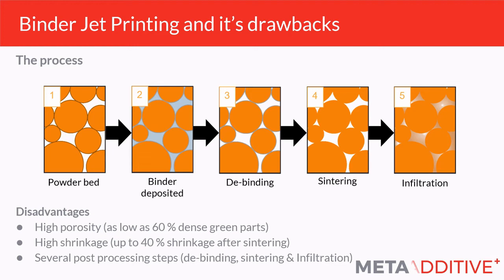You then need to heat treat it to consolidate the component to get a dense component. And again, these can sometimes be lengthy and high temperature processes. And this causes a high rate of shrinkage. So we can see anything up to 40% shrinkage for binder jet printed components. And again, this limits its size and the complexity of the geometry. We can use some careful models to try and predict how things may shrink. But the more complex the component, the bigger the component, the more complex that becomes,